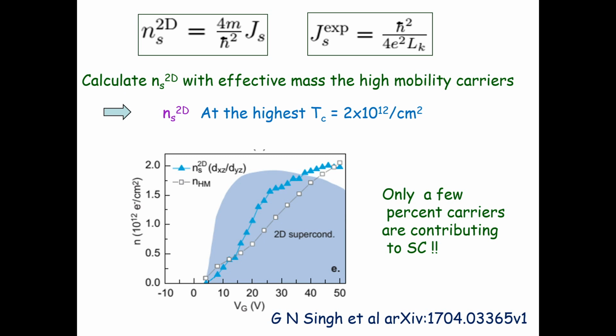And it turns out that the number density of carriers contributing to superconductivity at the highest Tc is only 2 times 10^12 per centimeter square. The measured carrier density from Hall is much higher than this. So what we are saying is only 2 to 3% of the total carriers are actually contributing to superconductivity. The rest are all forming the so-called low mobility background.